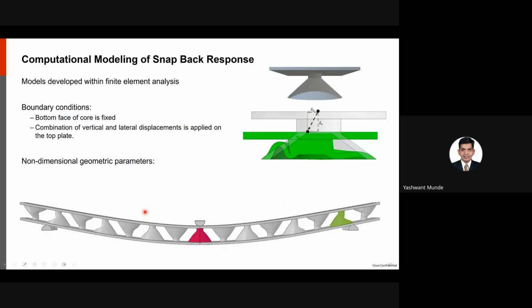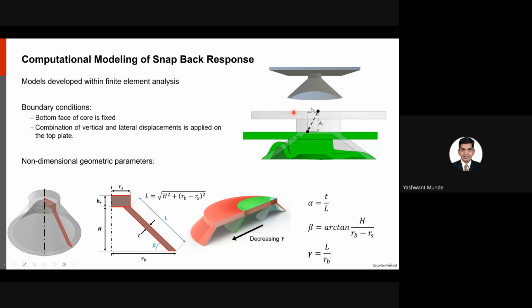Talking about simulation, we developed computational models to capture the snapback response, thinking of a sandwich core in mind, which can be subjected to a 3-point bend structure. We see that the unit cells can be subjected to both compression and lateral force in these regions. So we applied both compressive and lateral force individually on these to capture the effect of compression as well as shear on the unit cells. We non-dimensionalize these geometric parameters into 3, alpha, beta, and gamma. Alpha represents the thickness of the unit cell walls, T by L. Beta represents the slope that the walls make, H by Rb minus Rs. And gamma represents the curvature of these unit cells.